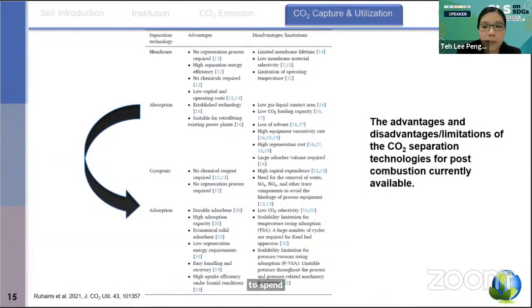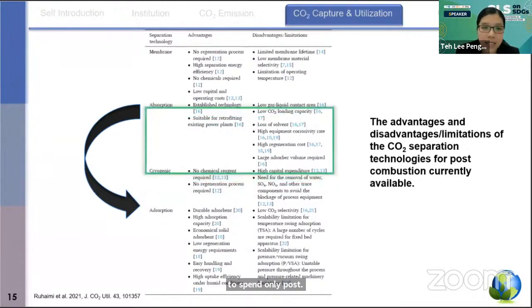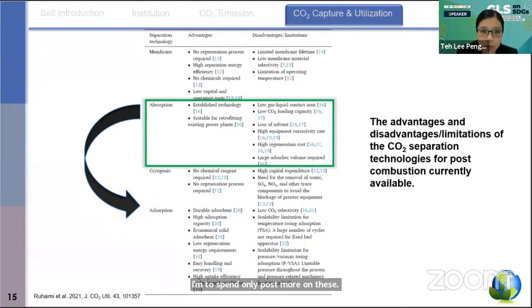To expand a little more on this, as demonstrated by these tables, we have the commercially available absorption techniques. Usually we call it the chemical absorption based. People usually use aqueous amine solution, such as 30% monoethanolamine (MEA) solutions. But this technique exhibits disadvantages like low gas-liquid contact area, low CO2 loading capacity, loss of solvent, high equipment corrosivity rate, high regeneration cost, and large absorber volume requirements.